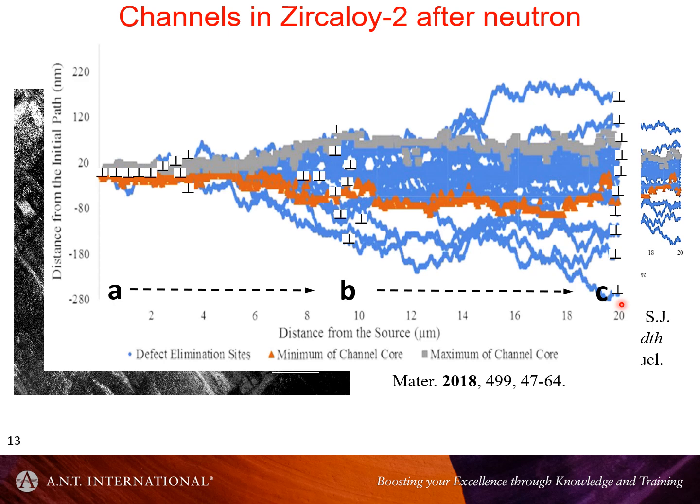So these dislocations are what is known as geometrically necessary dislocations, because this arrangement of dislocations in this way is the same as a subgrain boundary, and it actually creates a tilt in the crystal. Each individual dislocation does not tilt the crystal, but when they're in this arrangement and they've arrived at this arrangement through climb, in effect, by sweeping up the dislocations, this is a means by which we can get some tilting of the specimen. At this point here, we have a much more diffuse situation, and it's just like having this subgrain boundary spread over a wider area. It's a little bit more of a diffuse subgrain boundary.